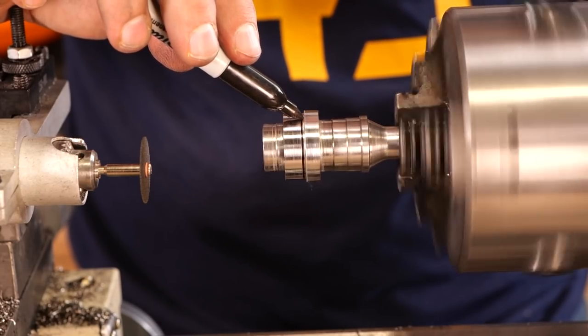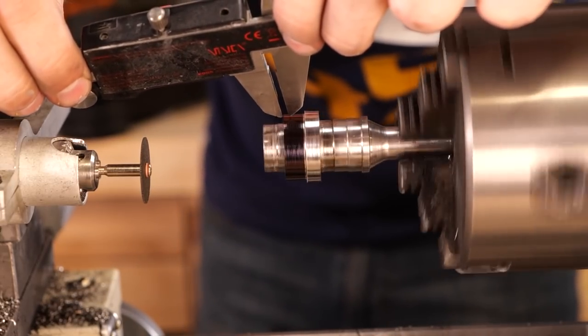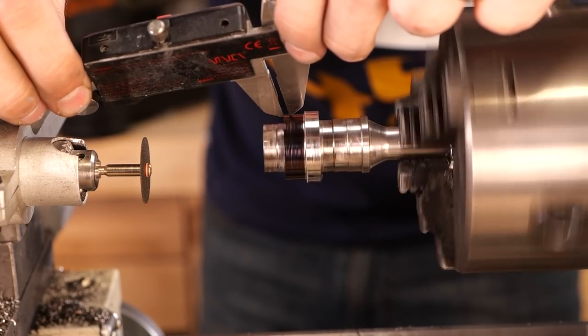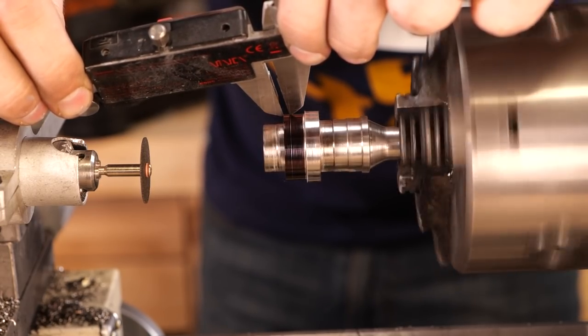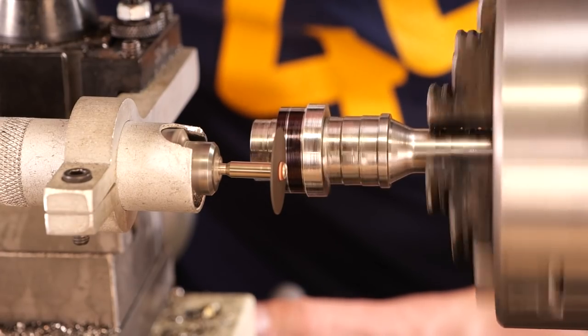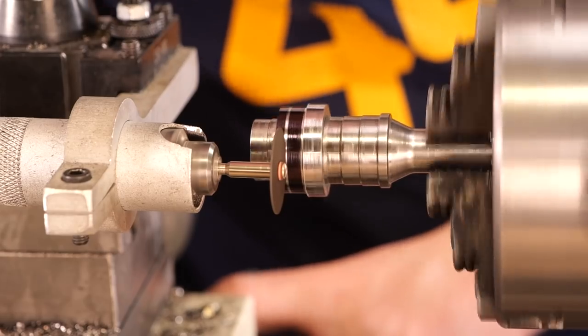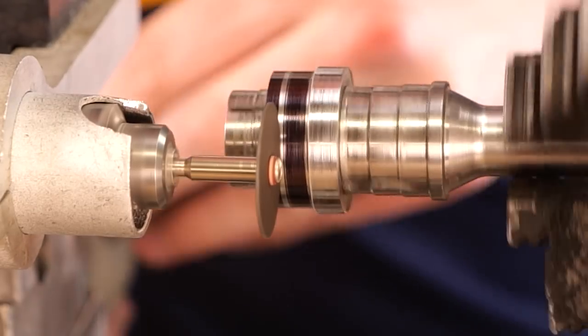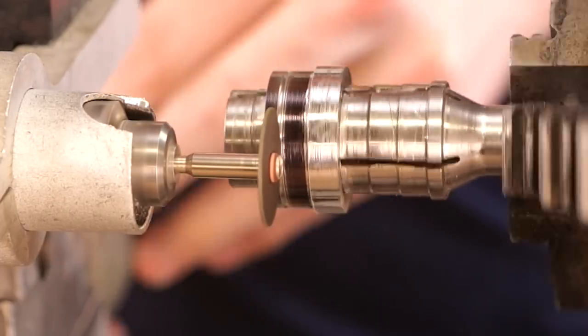Now I need to separate the pieces off, and I can't use a diamond cutter like I did for the carbon fiber because that just wouldn't work. The diamond would overheat and then the tool would destroy itself. So for this, I'm going to have to use aluminum oxide cutoff wheels. And the only problem with these is they don't last very long—they sand away as you use them. So it's quite a slow and tedious process, but the results are worth it. I'm going to go ahead and just take my time and we'll cut right through them.